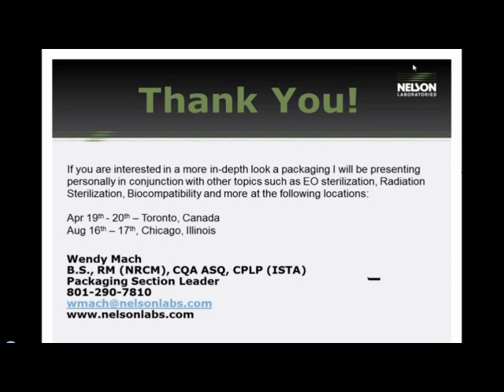How does Nelson verify the sensitivity of each of your packaging integrity methods? So the way the validations work, we identify thicknesses of wires, and we actually seal those into the packages. This is common. Everybody can do this. And then using our test method, we try to determine what is most frequently picked up in the test. And then tying that back to the specific thickness of the wire helps us determine the sensitivity of the test.